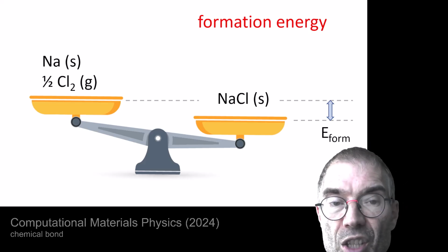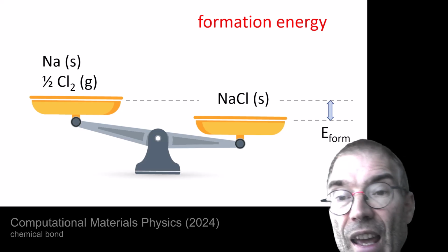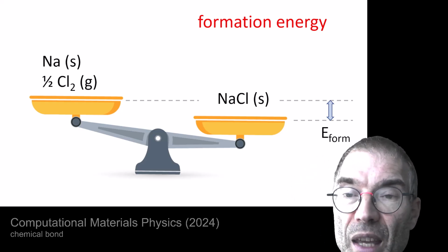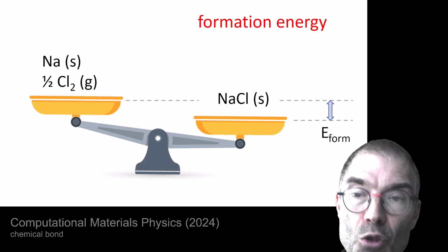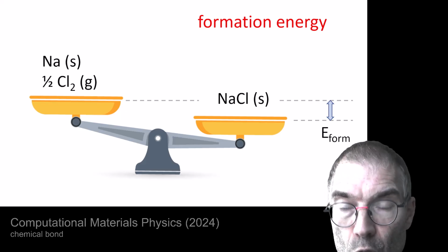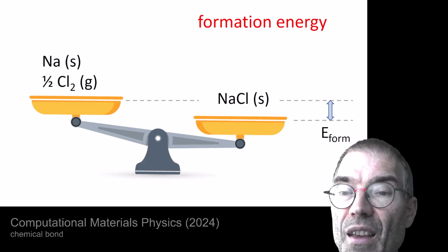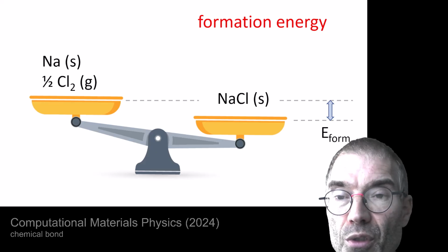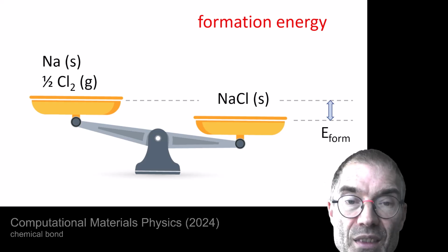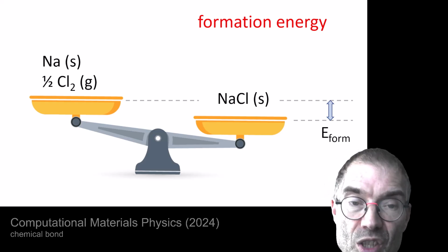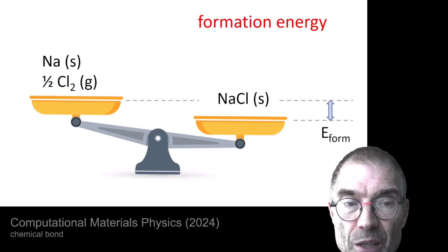Whereas the formation energy is the energy distance between the same crystal and now these elements that make the crystal, but in their elemental ground state. So you take solid sodium, an unary sodium crystal, and chlorine gas with Cl2 molecules. So the energy that is represented by these, and the difference between that situation and the rock salt crystal. That is the formation energy.